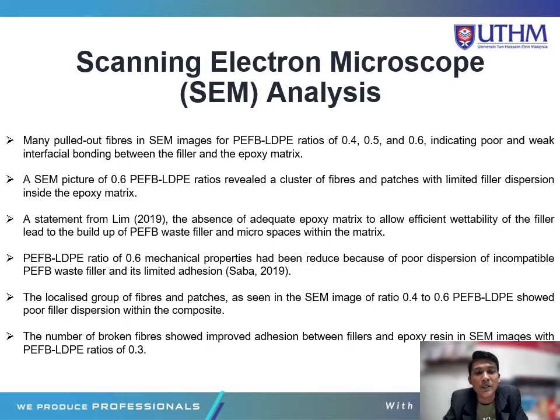Many pull-out fibers in the SEM images for PEFB LDPE ratios 0.4, 0.5, and 0.6 indicate poor and weak interfacial bonding between the filler and the epoxy matrix. The SEM picture of ratio 0.6 reveals clusters of fibers and patches with limited filler dispersion inside the epoxy matrix. A statement from Lim 2019: the absence of adequate epoxy matrix to allow efficient wettability of the filler leads to a build-up of PEFB waste filler and micro spaces within the matrix.